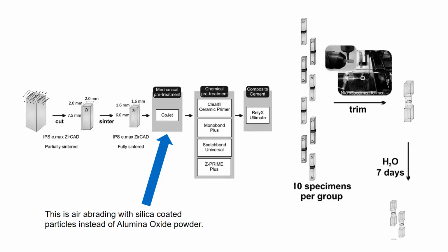That's what this is. So what they did is they took the Emax ZirCAD, partially sintered it, cut blocks, and then they finished sintering it. And then they did what's called a sandblast on it with CoJet. This is a 3M material that is silica-coated particles of alumina. And so they're abrading it with the alumina to expose the zirconia, but also some of those particles get embedded in. So you have kind of a silica and zirconia combined surface, okay?